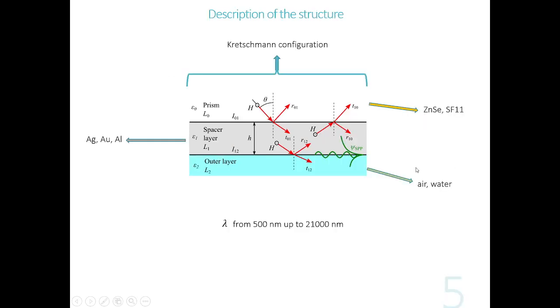So in the present research, the Kretschmann configuration was considered. For the prism layer, the refractive indices of zinc selenide and SF11 glass were taken, and air and water for the outer layer, air as a non-absorbing medium, and water as an absorbing outer medium. For the metal layer, three metals were considered: silver, gold, and aluminium. The sets of refractive indices were taken for the different fabrication types: evaporation, template stripping, and single crystalline growth. The simulation was carried out in the region from 500 nanometers up to 21,000 nanometers, up to the middle infrared.